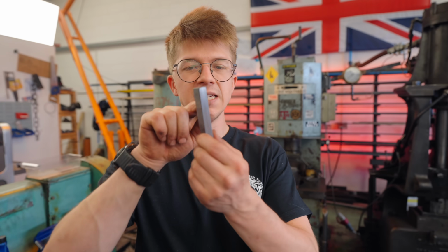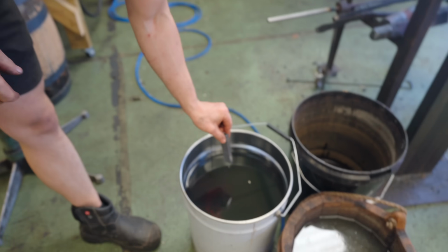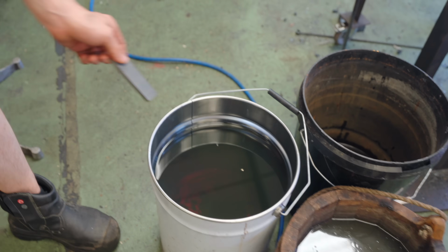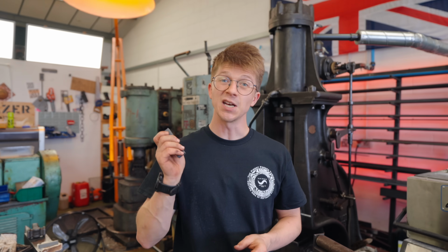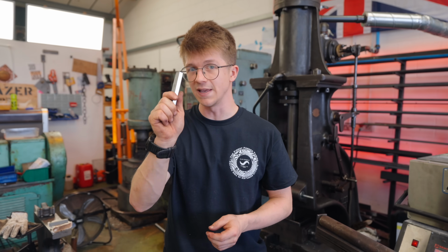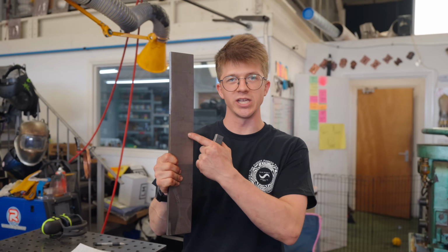We are obviously using a knife steel 1080 as the core here, but part of the reason why I'm curious about the hardness is it's got all this titanium on the outside of it. Titanium conducts heat a lot slower than steel. The worry is that as we quenched this, the heat transfer through the titanium wasn't fast enough to actually cool the steel enough to form martensite, which is the hard microstructure of steel. It appears that it was fast enough. So in this cross-section it works. We'll see how much that changes when we get to that one.